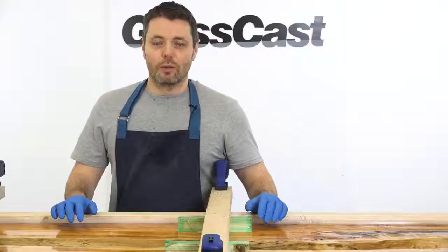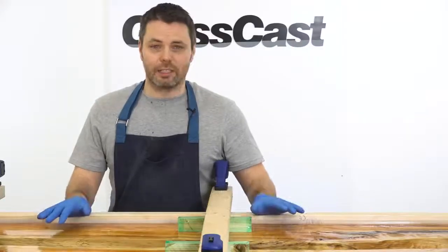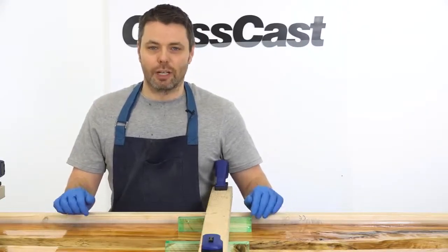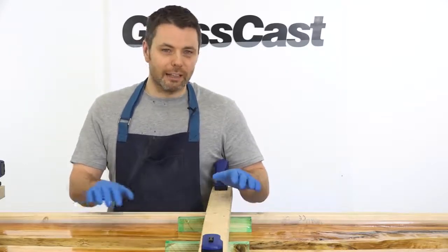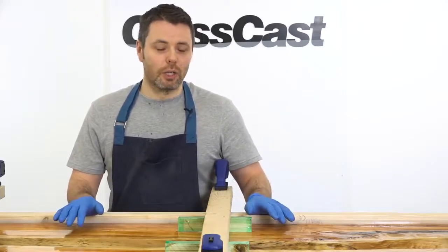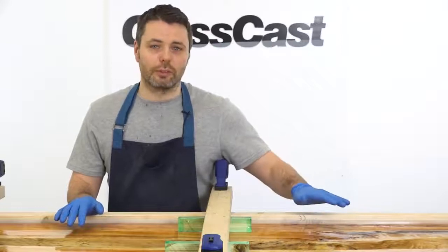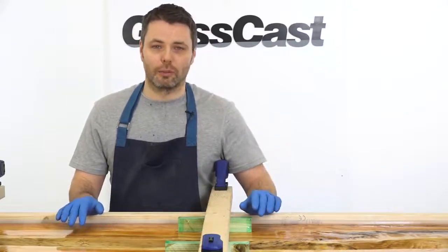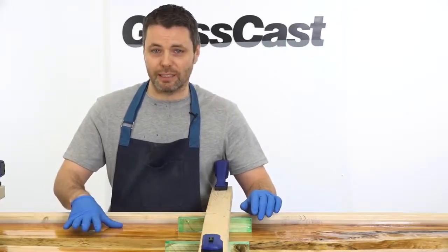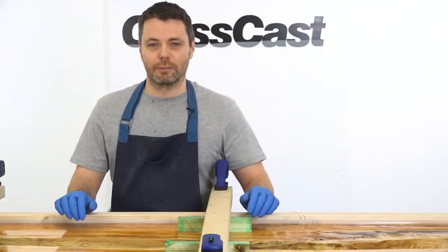Once you're confident that you're at the B stage, it's really important to move on with the final pour immediately. If we'd allowed this resin to fully cure, we'd have had to key the whole surface before we could move on to that final pour. However, because we're at the B stage, no further prep's needed.